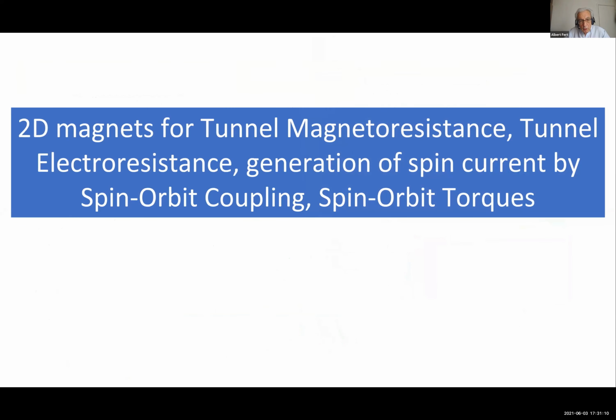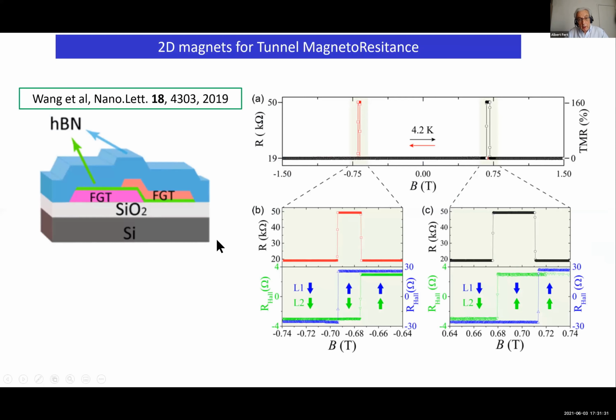So now we'll focus on several types of interesting properties. And I begin with the TMR, the tunnel magnetoresistance, and the electroresistance, the generation of spin currents by spin-orbit coupling, the spin-orbit torques, and this sort of interesting properties. So I begin with TMR, tunnel magnetoresistance, which is well known for 3D magnetic materials. And this magnetoresistance can also be found with 2D materials. This is an example in this publication of magnetic tunnel junctions with two electrodes of FGT separated by a single layer of hBN, this 2D insulating material. And so the properties are similar to those found with the usual magnetic tunnel junction.